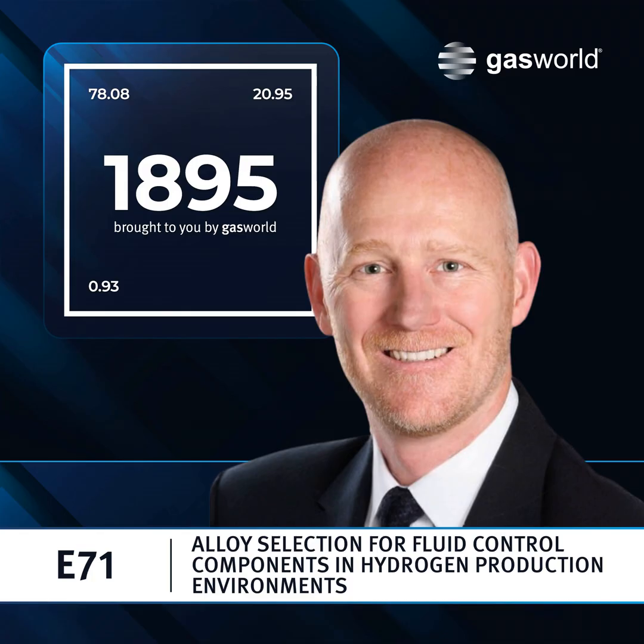So the fluid control systems at this point, especially sampling, they're not subject to those high temperatures, and so an appropriate high quality 316 stainless steel component works very well in this case, and allows the system to continue to be maintained. We at Swagelok have a special internal specification for our dual certified 316L, which includes a higher nickel and chrome content than the standard ASTM requirements, and that helps further improve things.